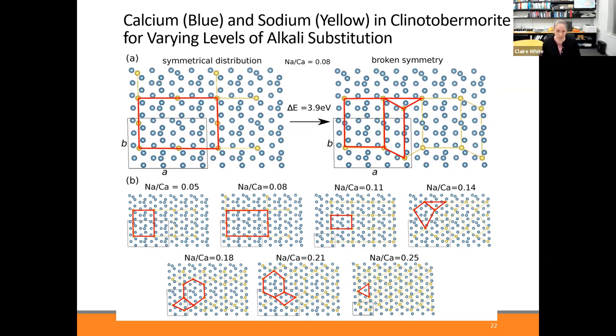We did it manually. What we found is the location of substitution does matter. If you think about this interlayer region that we have in these gels, there's calcium atoms in that interlayer region. Do you replace calcium atoms that are in the vicinity of each other, or do you replace calcium atoms as far apart as possible, for example? What we found here is we want to have a symmetric distribution of the calcium atoms to end up with a lower energy structure, meaning that it's more stable. Whereas if there's a less symmetric replacement, we found that the structure is less stable. So it's more stable when the replacement is symmetric, and less stable when the replacement is less symmetric.